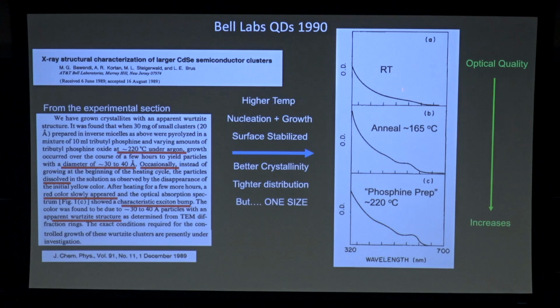You start to anneal it, you make the crystal structure a little bit better. There's a fundamental that starts appearing here, maybe a harmonic here, but a lot of noise here. With the phosphine prep at a higher temperature, that harmonic is better defined. We call that the exciton. That's creating that electron, freeing it up to fill up the box. Okay, that was good, and I did a lot of experiments in my postdoc with that.